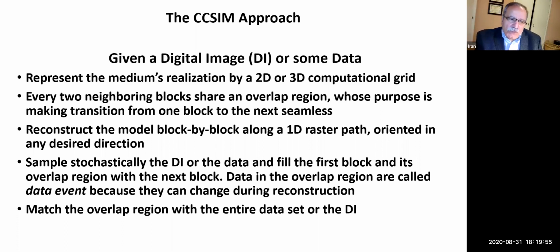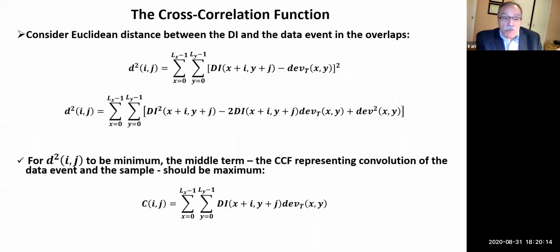And then what we do is we stochastically sample the digitized image or the data and fill the blocks and then match it with the data. The way we do it is to match the overlap region with the complete data set or the image that we have. In order to do the matching, we consider a Euclidean distance d between the digitized image and D_EV, which is the sample of the data that you have picked for a given block. Of course, we want this to be minimum because you want to be as close to the data as possible.